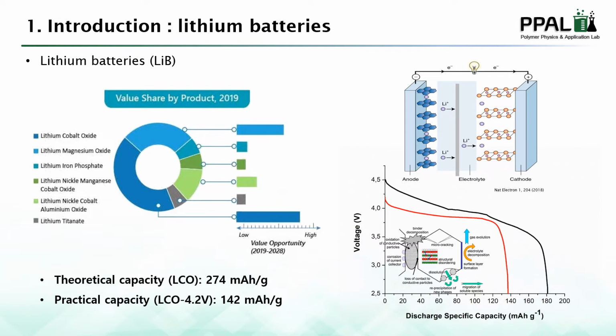Another problem we need to care about to maximize the capacity of lithium batteries is active materials. As noted, lithium cobalt oxide has been used as one of the most popular active materials for the cathode. And even though lithium cobalt oxide has a high theoretical capacity of 274 mAh per gram, its practical value has just been around 140 mAh per gram when it was applied at the upper cutoff voltage of 4.2 volts.